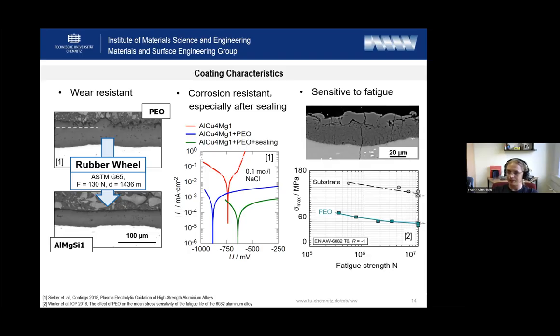And that's why we see here on an exemplary Wöhler curve of a PEO-coated substrate that the Wöhler curve of the PEO-coated substrate is significantly below the untreated substrate. So this is a challenge which we have to deal with. The theory behind is much more complicated. Residual stresses also play a significant role. And for further details, I recommend the literature of Lisa Winter, who is my co-worker and wrote her PhD project about this topic.